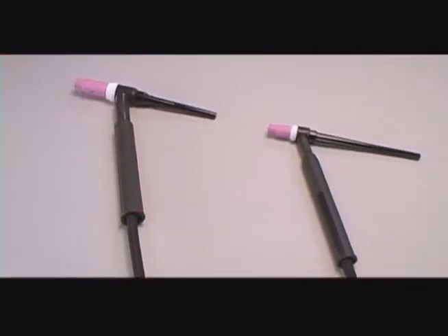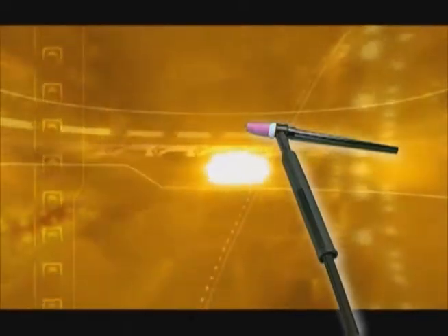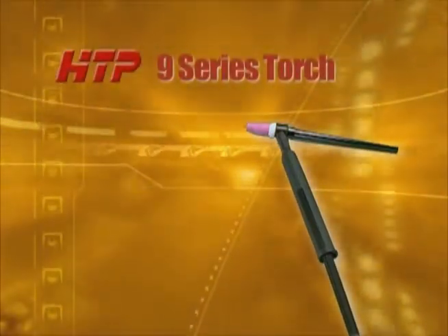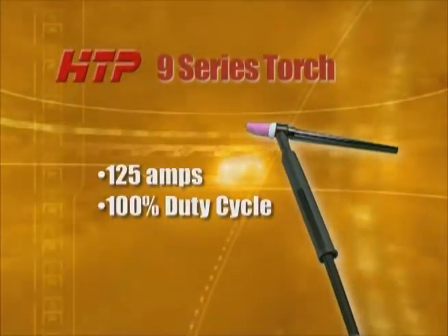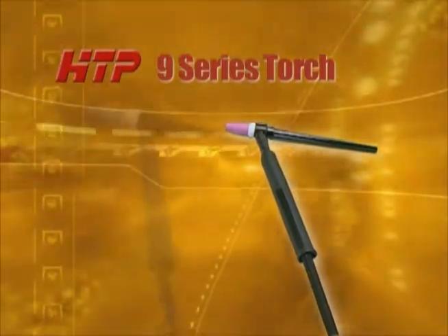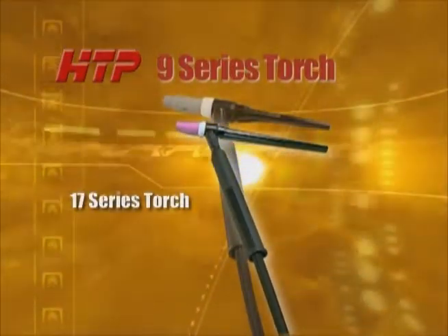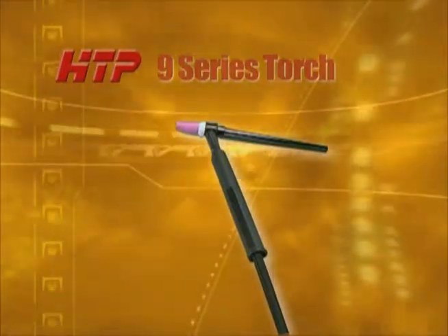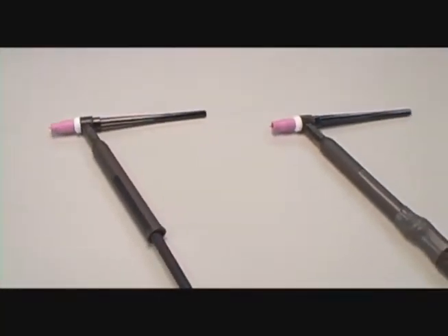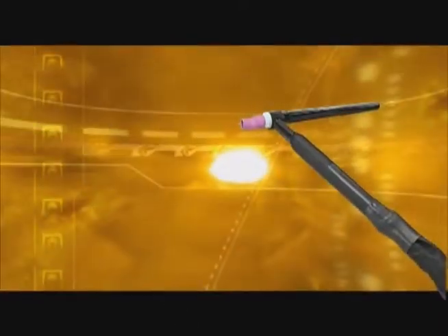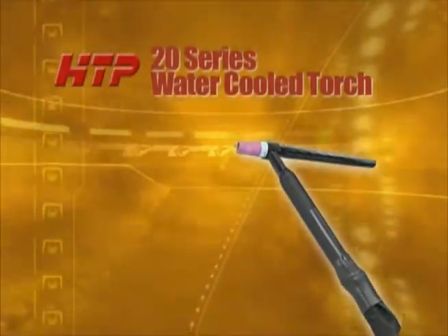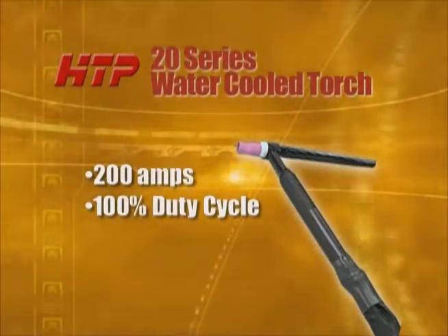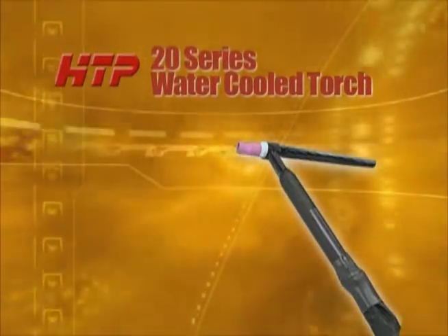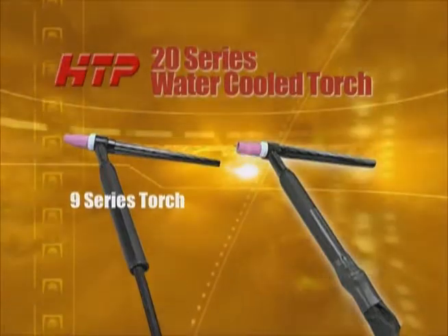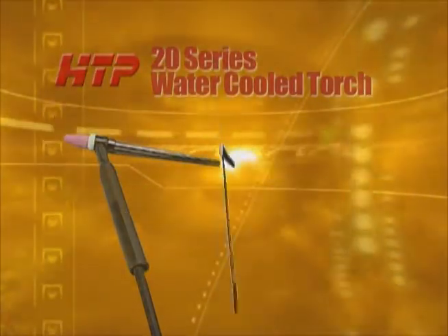Another common air-cooled torch is a 9 series torch, which is rated at 125 amps with a 100% duty cycle. You can see the 9 torch is smaller and will get into tighter places. This is a 20 series water-cooled torch. It is rated at 200 amps with a 100% duty cycle. It is the same size as the 9 series air-cooled torch and uses the same consumables.